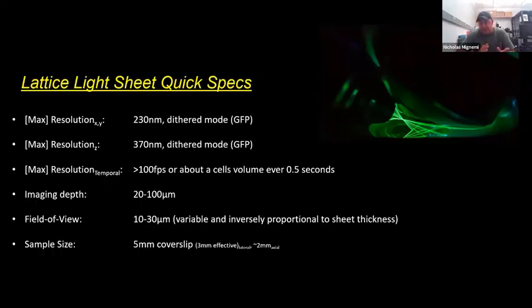I won't talk about frames per second because I know that doesn't equate to a lot of people. But given the right sample, our maximum speed for a cell volume is about every half a second, or every 500 milliseconds. And that's a full volume through the cell at 230-ish nanometers resolution. We image practically about 20 to 100 microns deep.